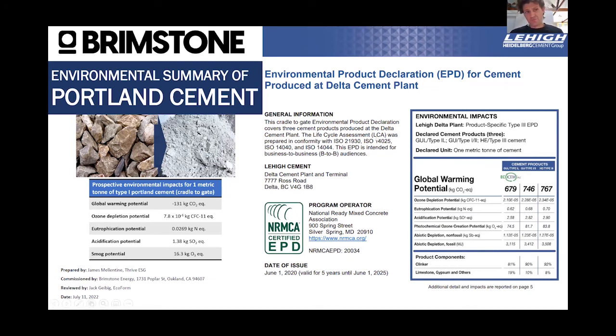I'm going to compare that to an environmental product declaration that I just pulled from the LC3 tool, which some of you might be familiar with, which shows a very good cement here. This is Lehigh's EcoCem, which is a very low emission cement, at 679 kilograms of CO2 per ton of Portland cement, so quite a bit higher, as you can see. So anyway, this was great news for us that a third party validated our result. It's a great milestone for the company. We're definitely excited to move forward with this process.